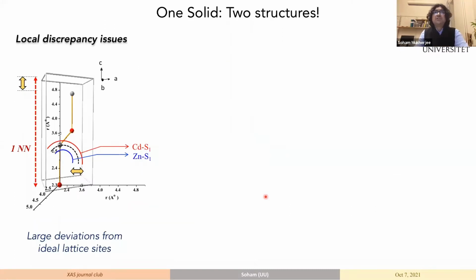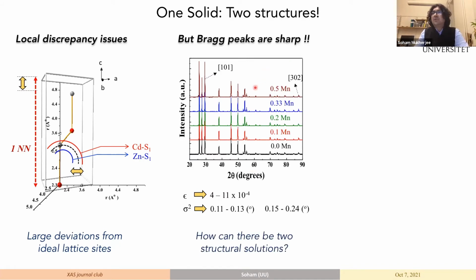So there is a very strange problem we are encountering now, because in an alloy system of zinc cadmium sulfide, instead of one atom position, there is a shell of sulfur which is farther away when we are looking at a cadmium site, and there is a shell of sulfur when we are looking at a zinc site. So how is the unit cell being maintained? Because when we look at the diffraction lines, we see that the microstrain is very, very low, and the Bragg peaks are really narrow, and we have the sigma square values for a very low angle and a high angle. You can always see that the sigma square values are extremely low. But how can there be two structural solutions?